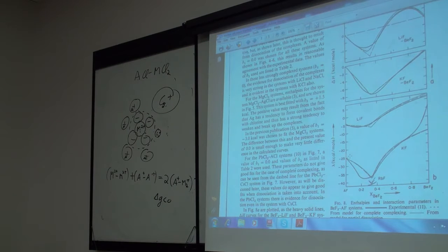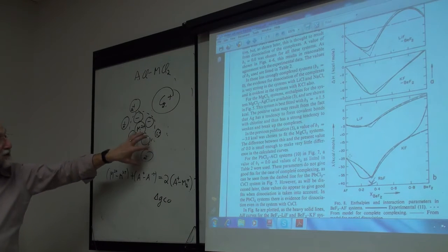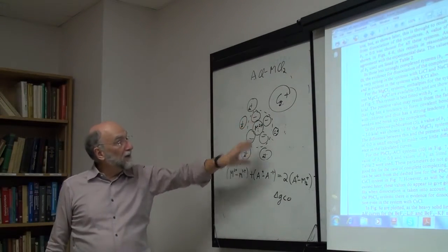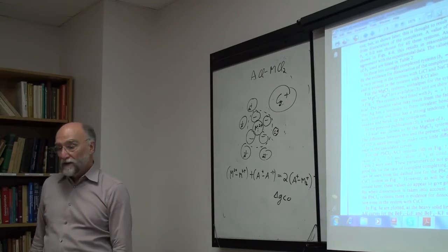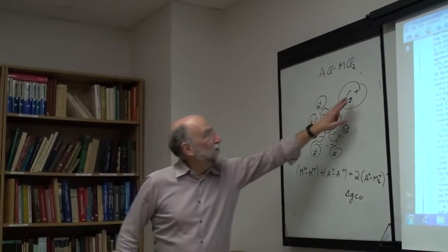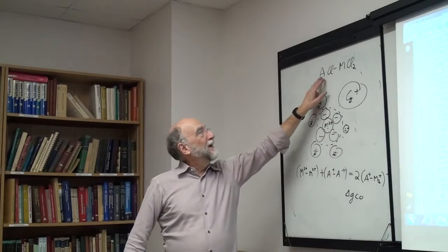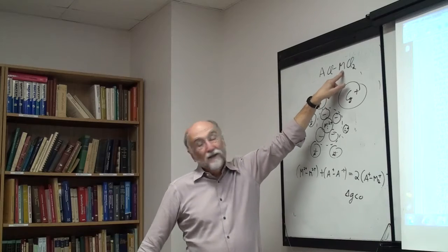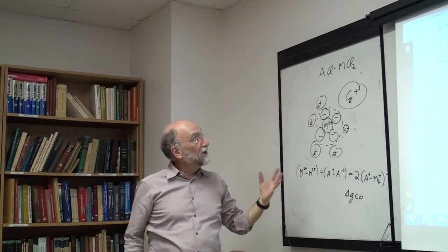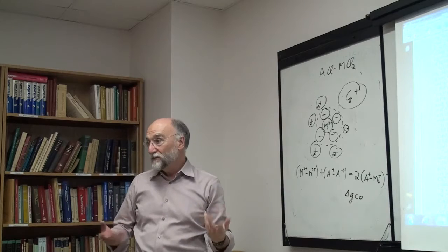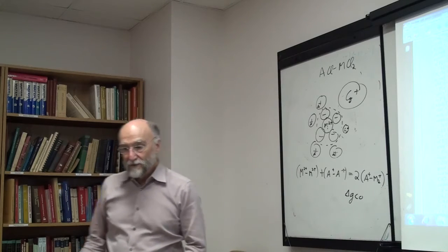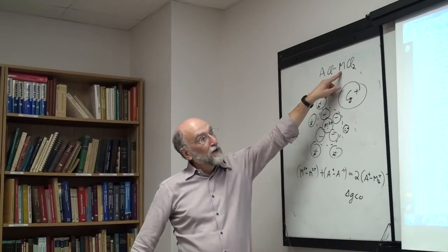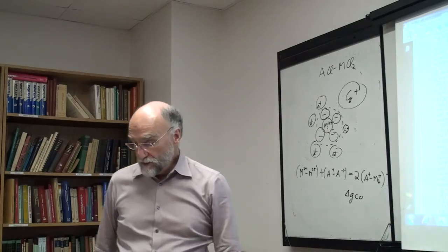When you get down to the bromides and the iodides, then you get these big ions, and with the big ions, in general, the bigger the ions, all interactions are weaker. If you have great big ions, the interactions are weaker. That's maybe just another way, if you don't even like this business about the cesium magnesium business. As you make A plus bigger, or you make the halogen bigger, or you make the M2 plus bigger, just all the ionic interactions are less, and so you get less tendency to form this ordering. Okay, so ordering, as you make A smaller, you make the halogen smaller, you make M2 plus smaller, you always have a higher tendency to ordering.